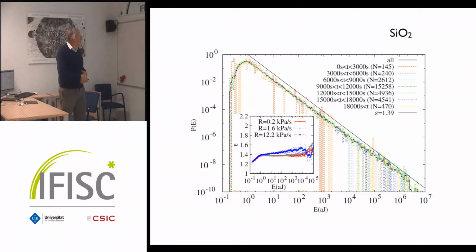And the probability function here, theoretically, should be a power law because it's scale invariant. And you see, it's a power law. And the exponent is 1.39. And as you know, the theoretical value for mean field is 1.33, 1.34. So we have basically mean field type of behavior, but over a huge range. And, you know, that is really, really new. Because a few years ago, we could do that on 100 data points or 500 data points. Nowadays, if we have less than 10,000, then my students say, oh, I can't do that. It's nothing. Right?